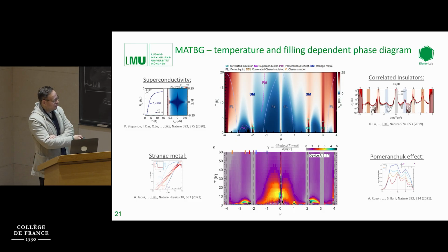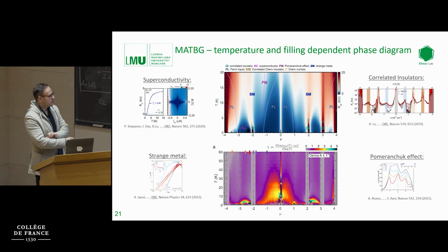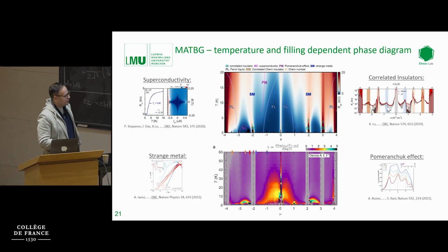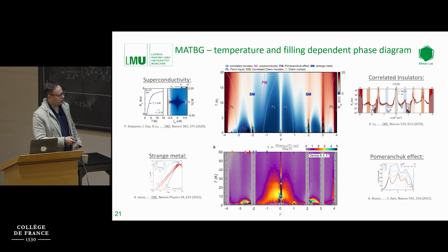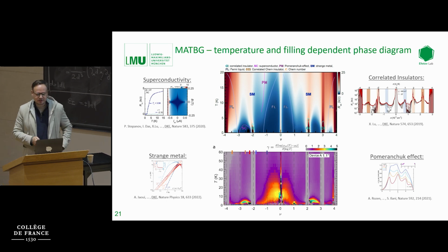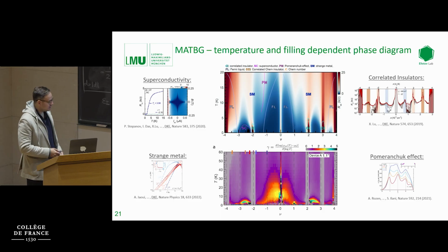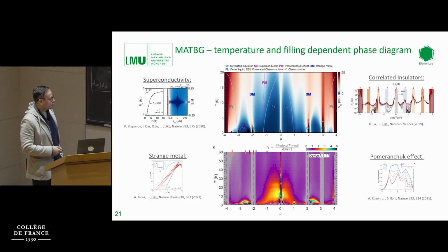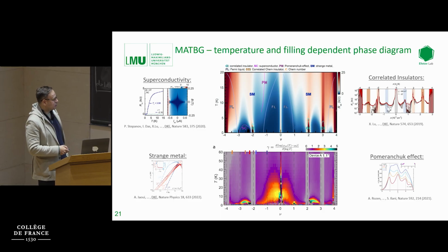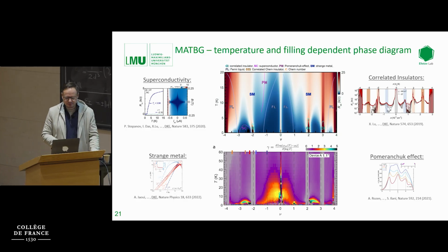However, there are phase transitions also in this linear-in-T resistivity. For example, closer to the charge neutrality point, we tend to see some T-square behavior and definitely not a linear T behavior. Everything else is governed by this linear T behavior. We discuss these metallic phases in a non-Fermi liquid-like context; potentially it's something one can relate to a strange metal.